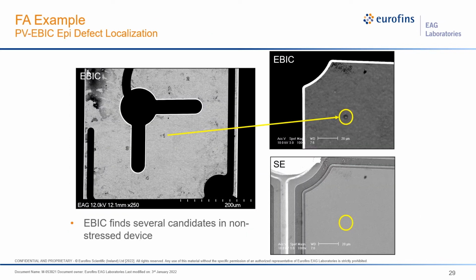So here's an example of us using SEM-EBIC on a known good LED, and we can scan this entire chip very quickly. And what we see is that the signal itself is actually very sensitive to changes in thickness. So areas that have thick metal on the surface, we're really reducing the amount of electrons and holes we can inject near the junction itself. So those appear very dark.